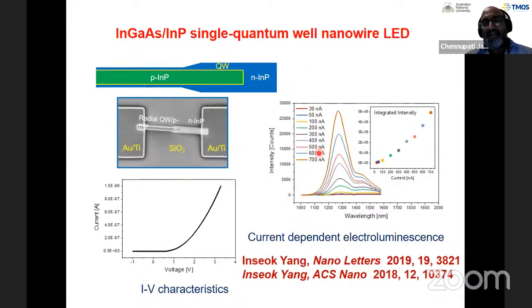So he injects the current into these nanowires and then looks at the light emission. You can see that as you're injecting more and more current, the light emission intensity is increasing as a function of injected current. You also see 2 emission peaks. It's mainly because you've got one axial quantum well here and one radial quantum well there. The thickness and composition of this indium gallium arsenide is different for the radial quantum well and the axial quantum well. So that's why you end up getting 2 emission peaks.